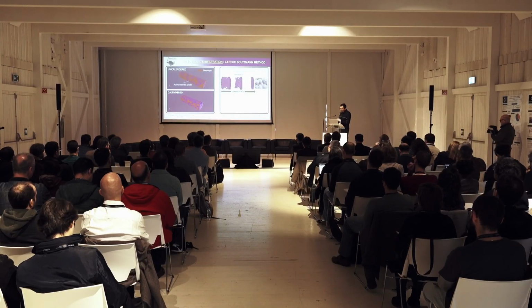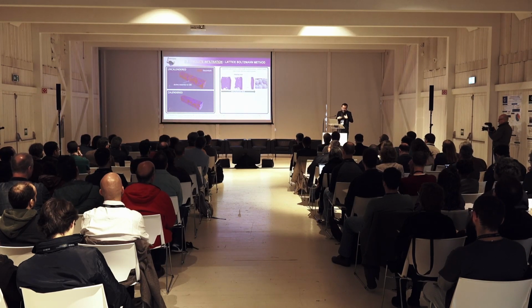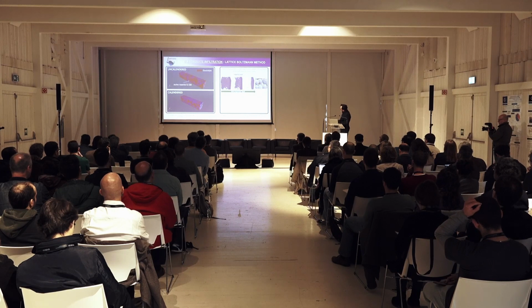How fast is the filling of an electrode when the electrode is not compressed? Because yes, here the porosity is high, and the tortuosity of the pore network is very low. And how slow is the electrolyte filling for the calendered electrode? Okay. Here this happens because the porosity is lower and the tortuosity is higher. You need, once again, to calender electrodes in order to improve the electrical contact between the particles, but at the same time, compressing the electrode means decreasing the porosity and therefore making the electrolyte filling more difficult, right?